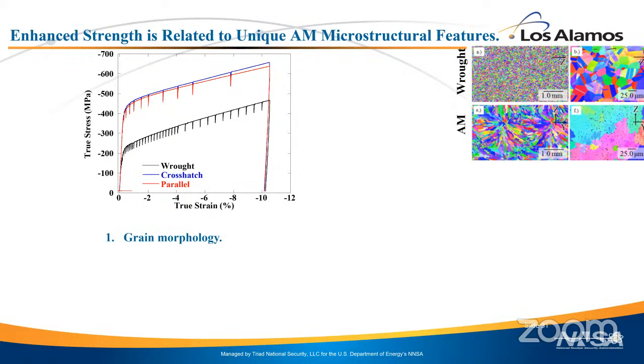Of course, you can just do ex situ microstructural things and you can get some of the answer. If you look at the microstructure of the AM compared to the wrought, you see they're very different. The 2 different sides, so up and down, are wrought versus AM, and then there are different length scales. The wrought material has a very equiaxed set of grains, and they're small. The AM material has a very tortuous set of grains, but they're in some sense quite large, and they have a lot of mosaicity to them. If you look on a smaller scale, you can see a lot of subgrain structure to the AM material that's not there in the wrought material. That certainly affects the strength.